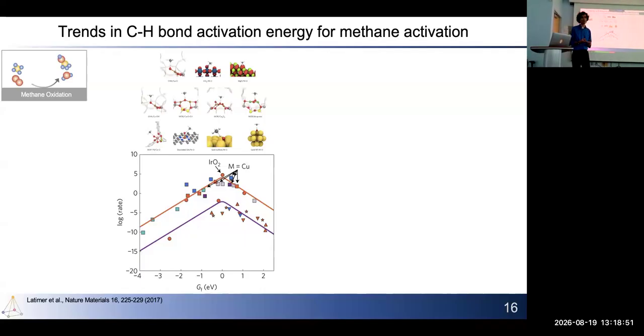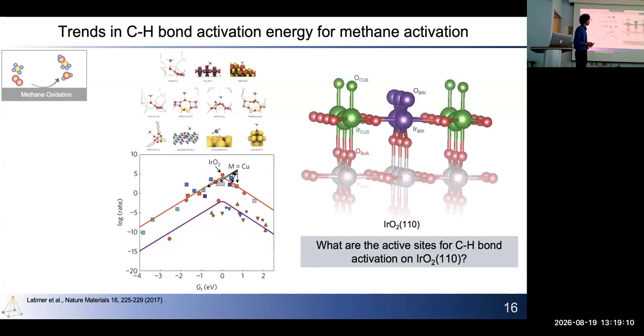So oxides, metals, metal organic frameworks, composites, and they ended up with iridium oxide being the one with the highest activation rate. That was a theoretical prediction, and then we wanted to go in and understand why iridium oxide works. So we took a closer look at the iridium oxide surface.